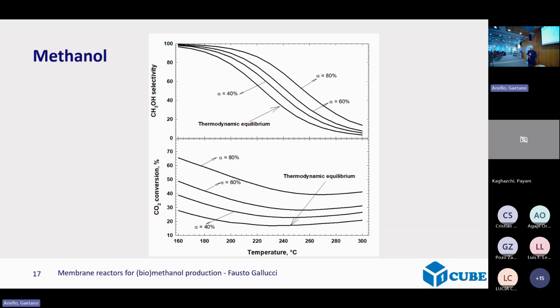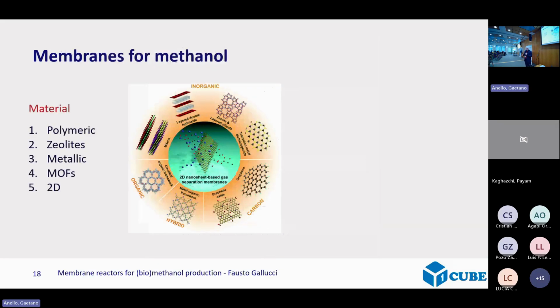So how can we separate this water? There are, again, a lot of membranes that you can use. Polymeric membranes, in principle, you could use, but this reaction is exothermic and needs at least 200 degrees to kick off, which means most of the polymeric membranes will not survive. But then you have a list of different polymers, different materials, zeolite, MOFs, and so on.